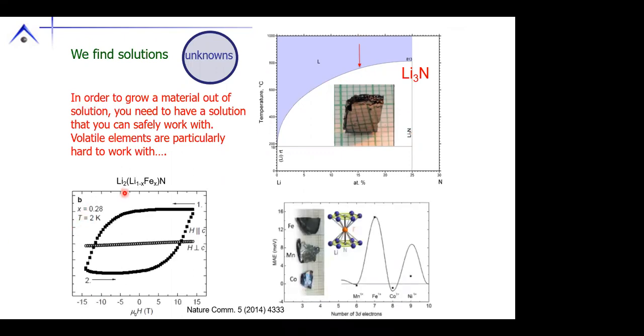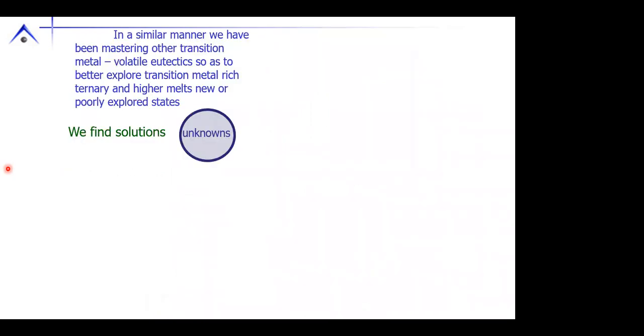So we realized this has 2 lithium sites. We tried doping in transition metals just to see what we can get, or can we grow a transition metal nitride? And instead we ended up with a doped lithium nitride, and we found out the transition metals in this rather exotic one-dimensional geometry have anisotropies, CEF split anisotropies that are larger than any known anisotropy for a rare earth. Absolutely phenomenal. Okay? Now, we can also extend this idea to other volatile materials.